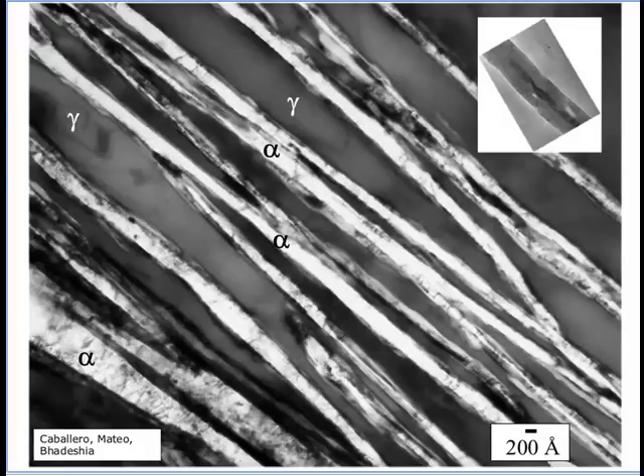The scale over here, this is 200 angstroms. And here I have a carbon nanotube at the same magnification. We have produced crystals of ferrite which are finer than carbon nanotubes purely by phase transformation. There's no deformation needed, no rapid cooling needed. It's a very cheap steel because we are stabilizing the austenite here using carbon.